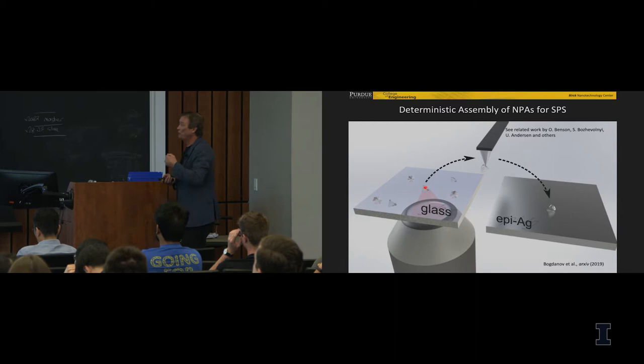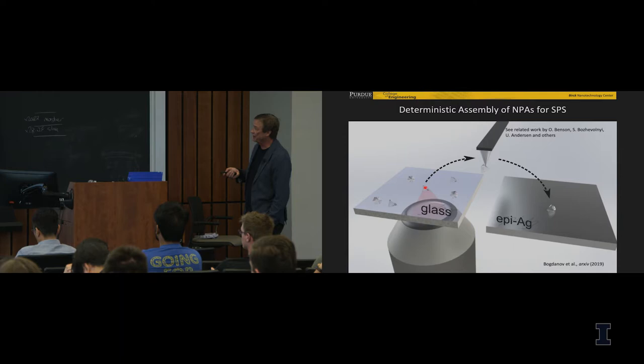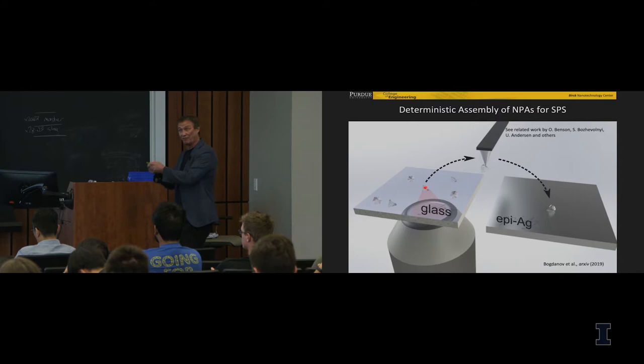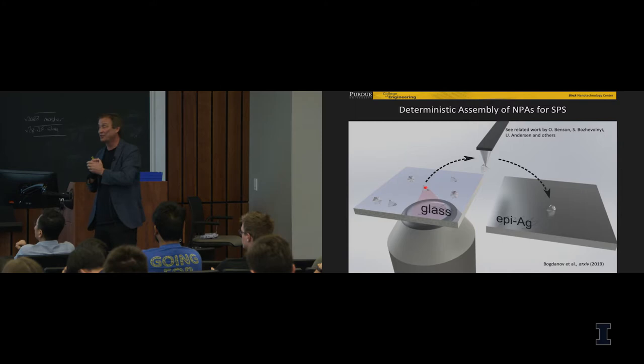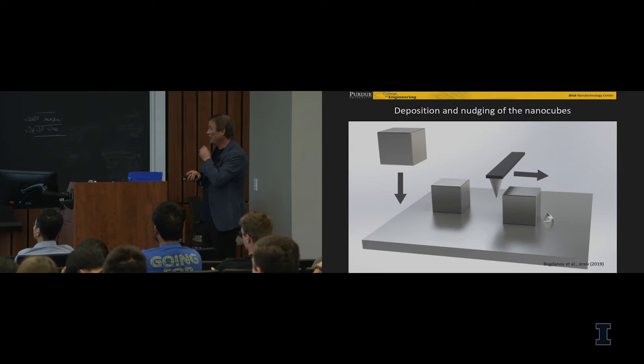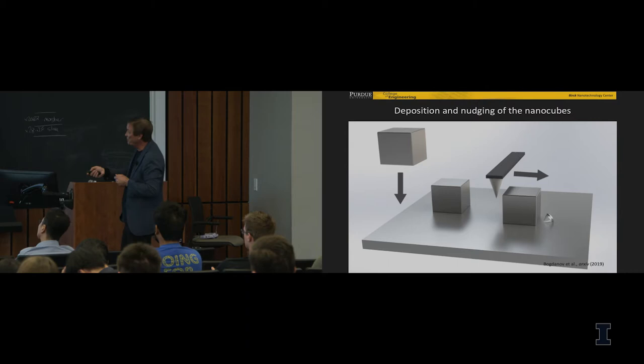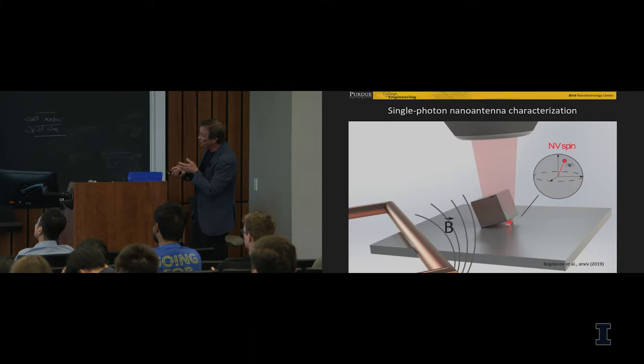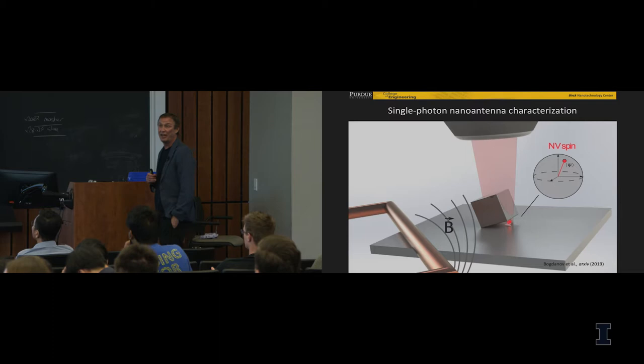So what we do, we first distribute these nanodiamonds on a glass substrate, then use an AFM tip to pick up a nanodiamond for which we checked the correlation function, and we know that it's a good source of single photons by measuring this G2, this anti-bunching correlation function, and place it on the epitaxial silver. Next, we place there cubes of silver, also single crystal, and with the AFM tip, just push it toward this nanodiamond, so that it climbs on top of this nanodiamond, and the nanodiamond sits exactly at the edge of the cube. That's where the Purcell enhancement is the largest, as calculations show.